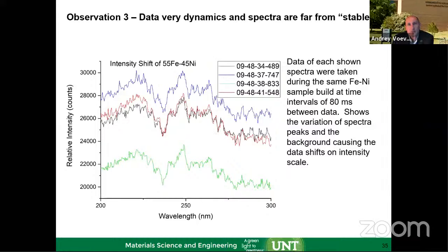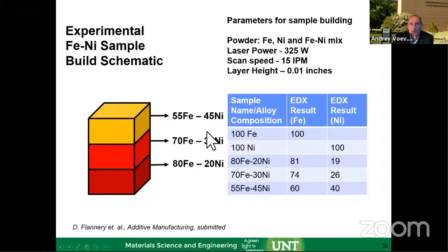So it is not that simple, and I think it all comes from the fact that additive manufacturing is a very dynamic process by itself, because you're sintering powders. Powders have different sizes and distributions, and that all affects the plasma signal. Nevertheless, I said, okay, we'll try to do it in a gradient experiment and see if we can correlate some of the gradation of the powder feeding to the gradation of the intensity of the lines we're detecting. So we made this experimental setup for the fabrication of an iron nickel sample. In that particular schematic, the build starts with the powder feeding from the bottom up.